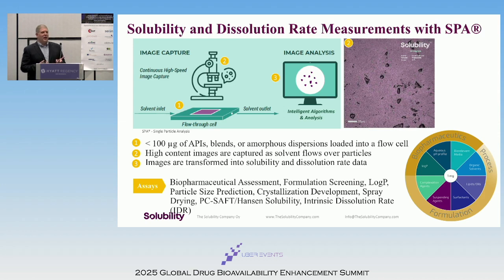Let's say you don't have much material, and your compound is highly soluble in some of your solvents that will dissolve before you cool down or add a co-solvent. You just need 100 micrograms to get that solubility information right up front.